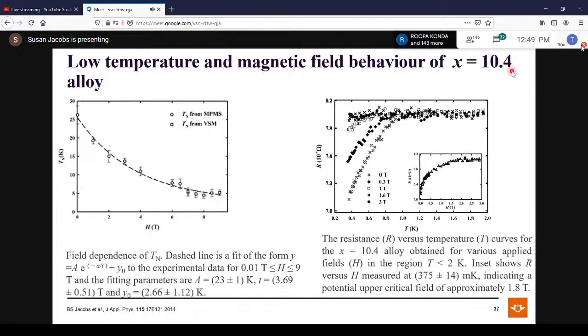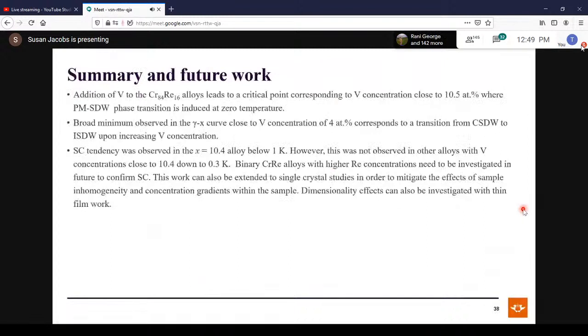But we made more samples in this vicinity, and we could not see superconductivity even down to these very low temperatures. So what we think is happening in this alloy is that there may have been a binary chromium-rhenium cluster, which became superconducting, and it's not the entire alloy that is superconducting.